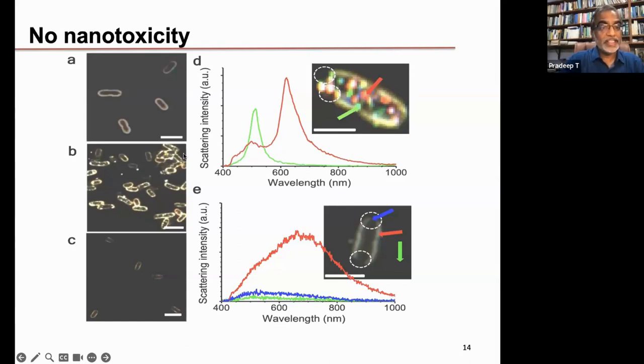But in our case, materials are there, bacteria are put in, the bacteria get killed, and that is what you see in this kind of lysis that you see in dark field microscopic images and spectroscopy, but no nanoparticles. So this killing happens because of ions and not nanoparticles. No nanoparticle release occurs and there is no nanotoxicity. So it can be implemented in the field, and we did implement.